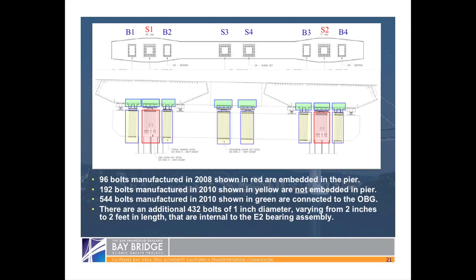And as you can see here, in terms of the green areas, there are another 500 bolts, also manufactured in 2010, that connect those shear keys and bearings, the upstairs bolts, to the deck that's above it, the steel deck, and above the steel deck is the riding surface that you drive on. In addition to those, there are also an additional 400 or so bolts that are smaller. All the bolts that I've described so far are roughly 3 inches in diameter. The ones that go through the pier cap are very long. They're 15, 20 feet long. The upstairs bolts are much shorter, but they're as wide in terms of diameter because they have a very small distance to cover just to connect the bearings and shear keys to the OBG.